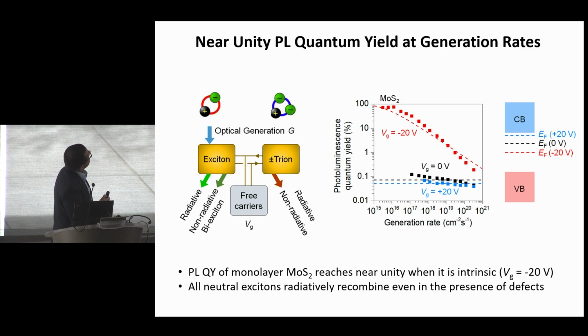And so what we see is, if we can form our particles mainly in the form of neutral excitons, the material is purely bright. The process is purely radiative. And on the other hand, if we form charged trions, the process is mainly non-radiative. And this is expected because this looks like an Auger recombination. If you think about it, two electrons and a hole, that's how Auger recombination looks. So we can make these materials bright if we can form neutral excitons as opposed to charged trions.